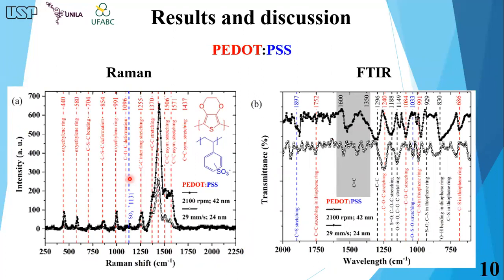It is worth saying that thick films were used in order to have more noticeable peaks in this spectra. Despite the addition of IPA for blade coating deposition, the relative intensity and position of the peaks remain unchanged. In summary, even after IPA addition and thermal treatment, it can be inferred from optical characterization that the chemical structure of PEDOT:PSS was preserved during processing.